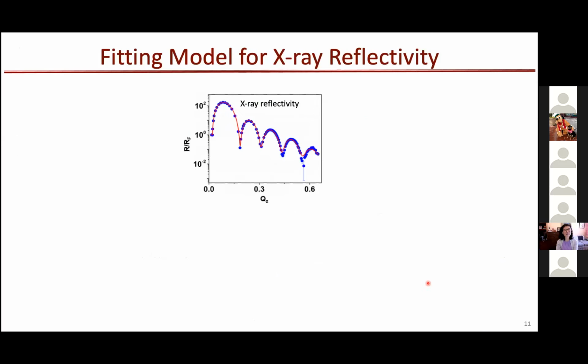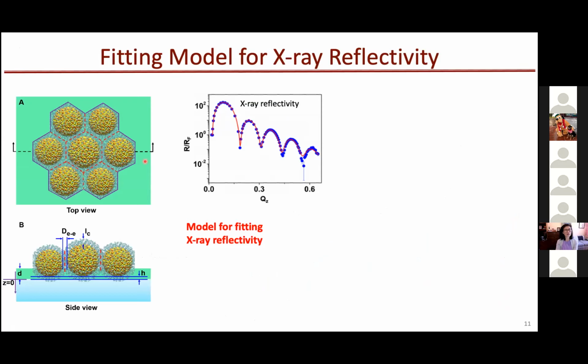Now we'll look at the fitting models for X-ray reflectivity. The model we use is illustrated here: this is the top view for the gold nanoparticle, and this is the side view. First, we introduce the size distribution in the fitting, and then we allow the free thiols, represented in green, to fill between the nanoparticles.